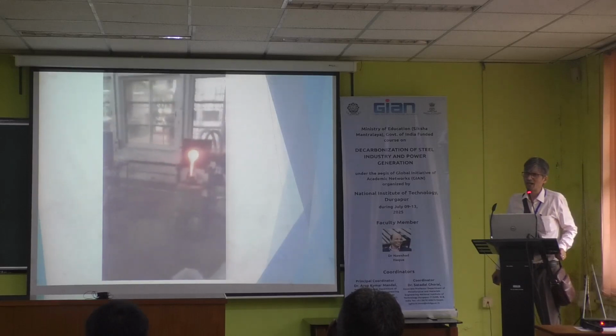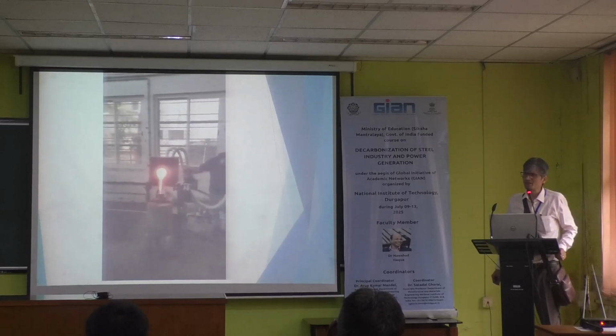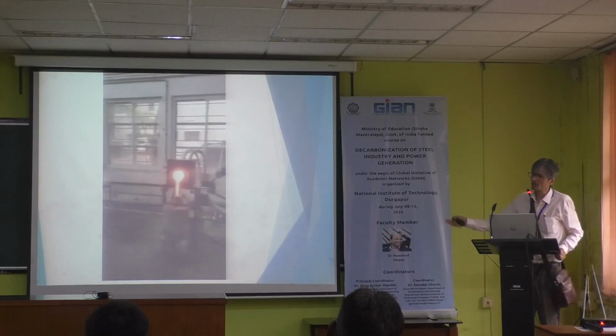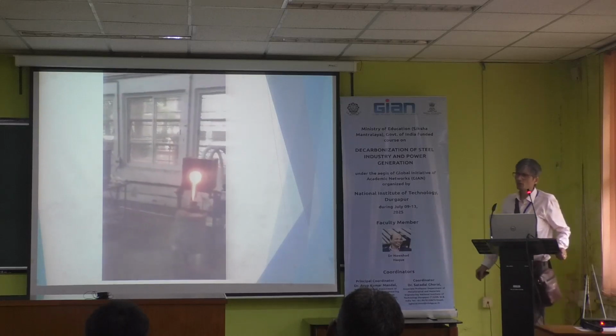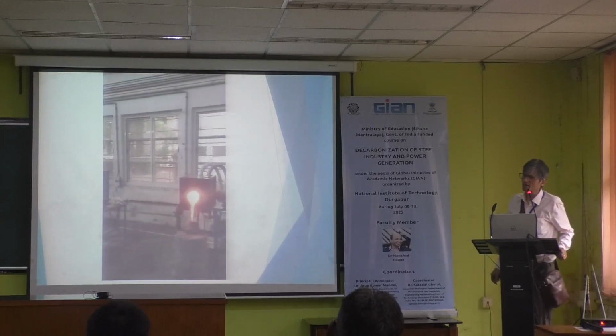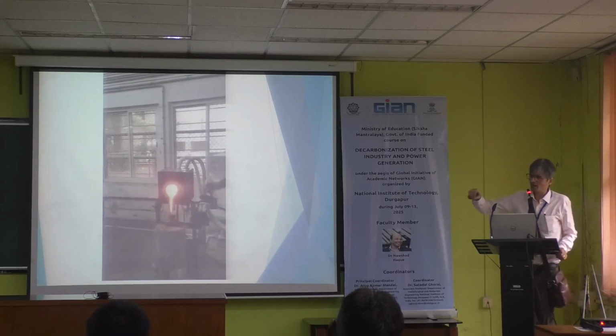But again, I think the dissolution is taking a longer time. A lot of silica is getting evaporated. So we are looking for some ready-made synthetic slag that, if you add it, gets dissolved and is able to capture the phosphorus.